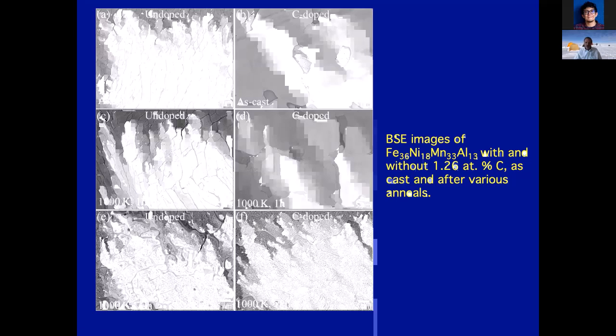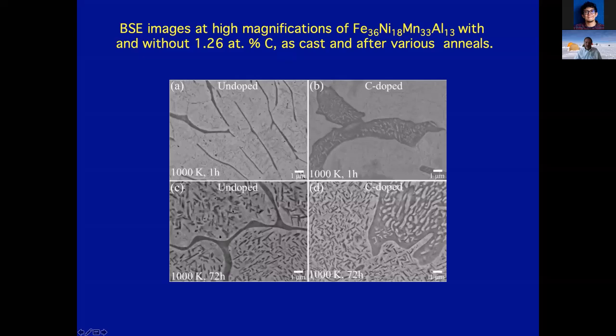This is the same second phase, it's just the B2 phase that we saw before after tensile testing at higher temperature. So this is a higher magnification. This is the undoped, the initial original lamellae, and then after we anneal it, you can see more B2 phase forming here. This is the carbon doped, where we've got this B2 phase forming in the matrix, and we've also got some other precipitates forming within these particles themselves. So it turns out that by adding carbon, we ended up with a 3-phase microstructure of a matrix of FCC-B2, some particles in there, which also themselves have particles in them.